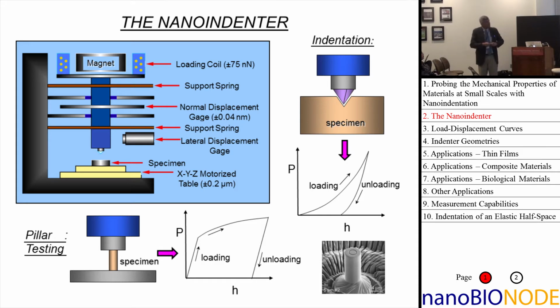The device down here is, in fact, a diamond indenter. And that indenter is then pushed into a specimen. What makes this different from normal hardness testing is that as we're pushing it in and withdrawing it from the specimen, we measure the displacements of the device so that we can get force displacement curves as we're pushing the indenter in.